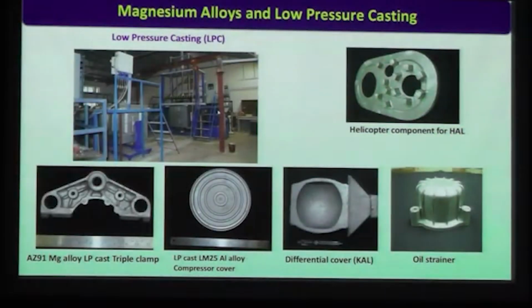We also have liquid low pressure casting techniques for magnesium alloys. Again, magnesium alloys are even lighter when compared to aluminium. Here, as I mentioned, the first component is a helicopter component for HAL. At the bottom we can see a lot of automotive components which were developed using low pressure casting. There is AZ91 magnesium-aluminium-zinc alloy for the triple clamp. Then LM25 low pressure cast alloy for compressor cover, differential cover, and oil strainers, mostly for the automotive sector.